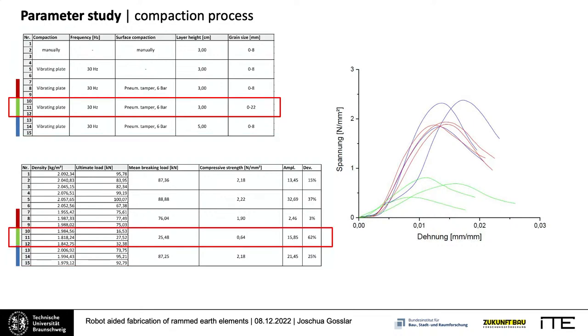So the next 3 specimens here, we see that the material was just too coarse. We used a material of 0 to 22 millimeters with a layer height of 3 centimeters, and that led to very low compressive strength and also very high deviation. So there's a boundary reached, let's say. And then the last 3 specimens where we used the same setup, we had 3 centimeters of layer height, up to 8 millimeters of grain size, and we achieved a reasonable compressive strength for our first tests and a deviation of only 3%. You see the red lines on the right, they're quite in a similar range, and that's what we actually aim for. So this is our benchmark value from where we want to go further.